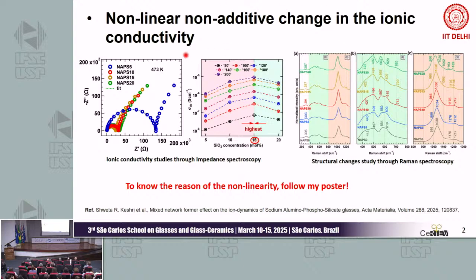Yes. So as you can see in the first figure, I have used impedance spectroscopy to calculate the ionic conductivity of the glasses. We can see that instead of a linear trend in the ionic conductivity, there is a nonlinear trend. One of the glass compositions gives the highest ionic conductivity, followed by a further decrease.